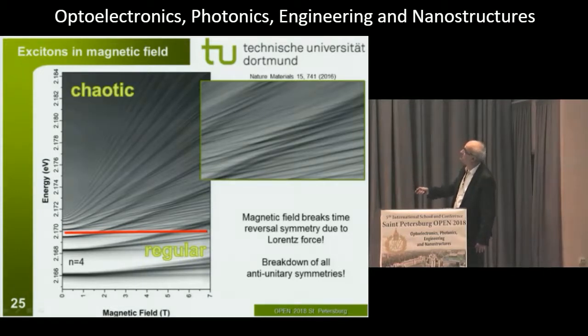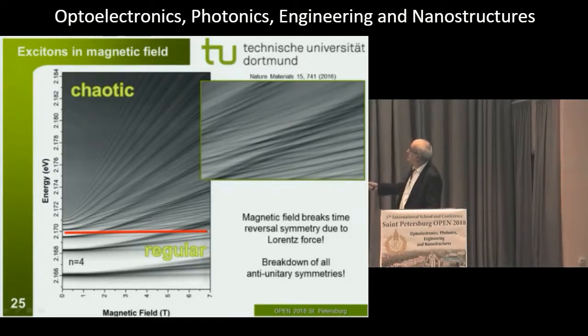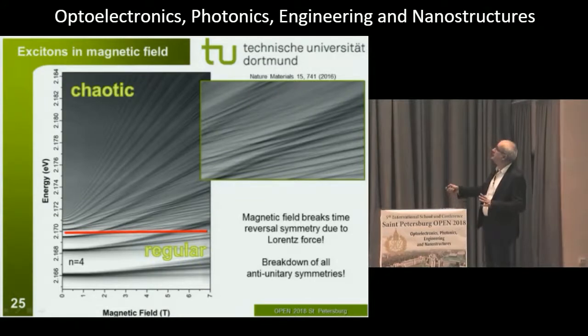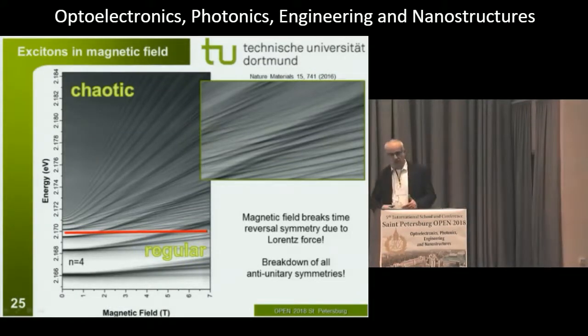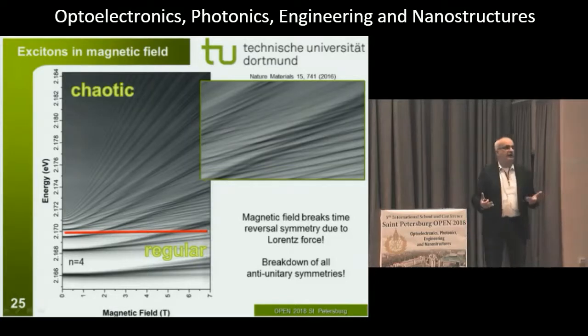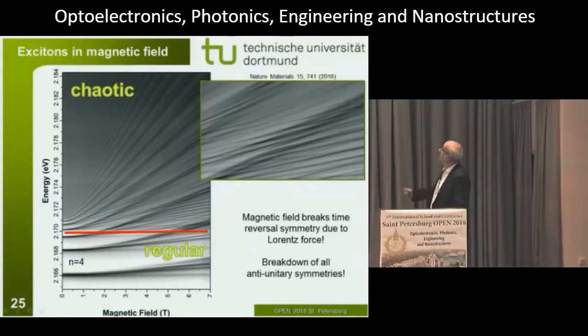This is zero magnetic field. So here we would have our hydrogen series, and then we apply a magnetic field, and you see first a high energy shift, which is a diamagnetic shift, and then you see a spin splitting. Below this red line, which is below n equals 6, your spectra look more or less okay. And above the red line, all hell breaks loose. As you can see, for example, this is a close-up, a small zoom into a small area here. Actually, we wanted to go very fast to interaction phenomena, but then we got stuck here. What happens here is that you have no longer a regular motion that you could easily describe and solve by Schrödinger's equation, but you have quantum chaos here.